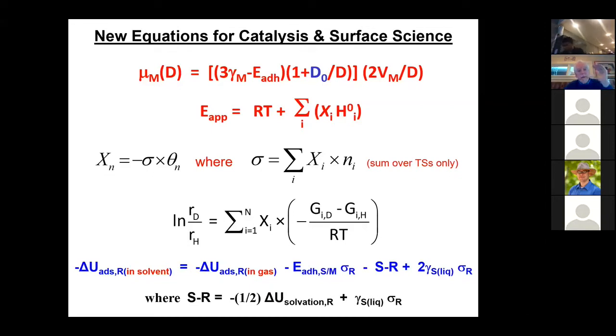The hydrophobic effect causes it such that even at 10% or 5% of saturation coverage of the organic, it's already in high coverage islands that aren't going to get any higher in coverage. And I don't know if that high coverage is as high as what you get when you do the experiment in the gas phase. It might be quite a bit lower because you get too close together and there's too much repulsion and you can't get any closer than that. But the coverage effects might be less, I'm guessing, in solvents because of those effects than they are in the gas phase.